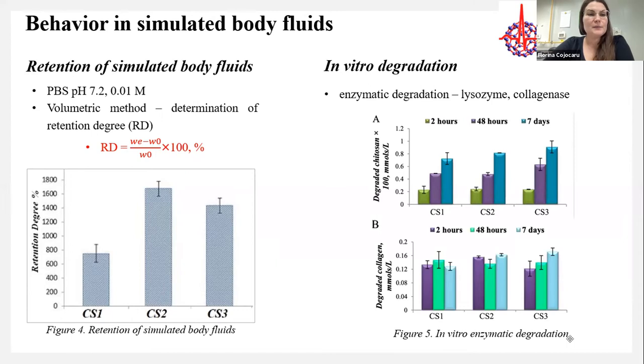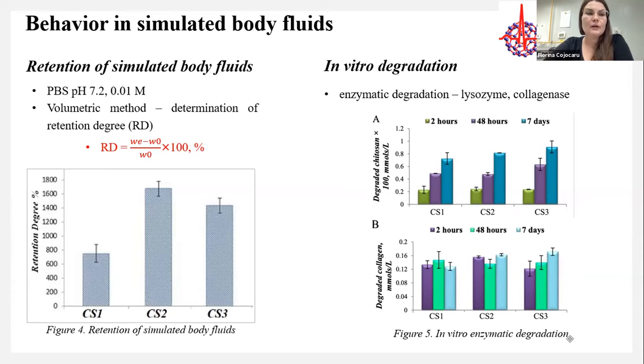In vitro degradation was studied using an enzymatic mixture containing lysozyme — the enzyme that degrades chitosan in vivo — and collagenase — the enzyme that degrades collagen in vivo. The data obtained for in vitro degradation, shown in Figure 5, can be attributed to the retention degree, because the high retention degree allows enzymes to penetrate within the composite scaffolds and leads to uncontrolled degradation.